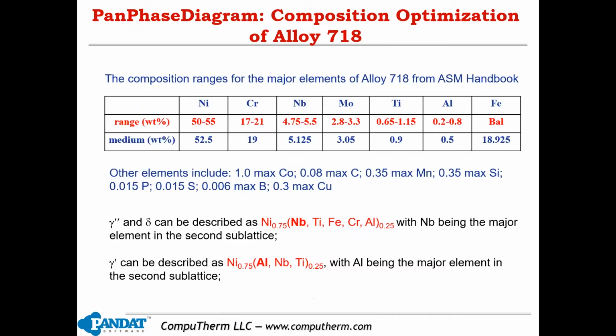So if you work on nickel-based superalloy, 718 is a very popular alloy. And as we know, commercial alloys usually have a spec range. Here in this table, it lists the composition range of 718 alloys. So as you can see, nickel can vary its composition from 50% to 55%, and then chromium from 17 to 21%, and so on and so forth. And aluminum is a very small amount from 0.2 to 0.8%. So many people would think, okay, this small variation will not do anything, right? But actually, this is not true, okay? We can find out that this small variation of aluminum will play an important role in the microstructure development.